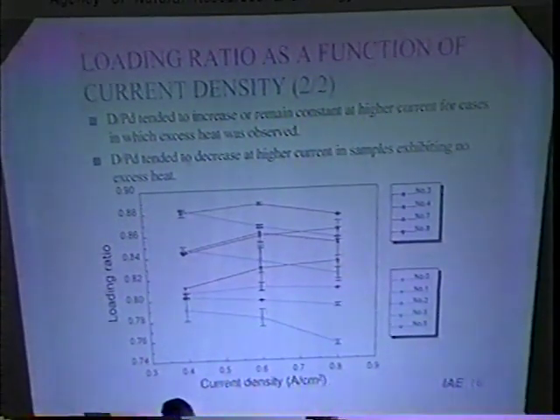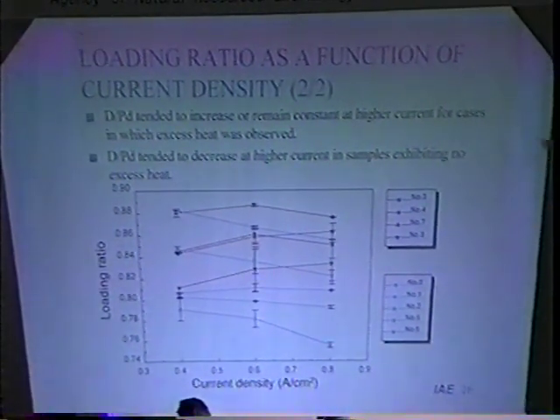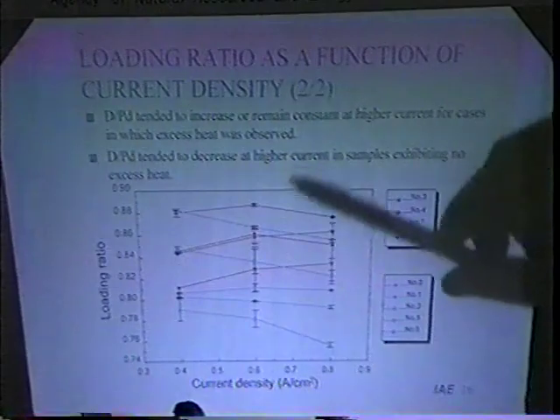As shown in this figure, the red data belong to the samples in which excess heat was observed. The blue data belong to the sample without excess heat. The D/Pd for cases in which excess heat was observed tended to increase or remain constant at higher current. On the other hand, the D/Pd without excess heat decreased at higher current.